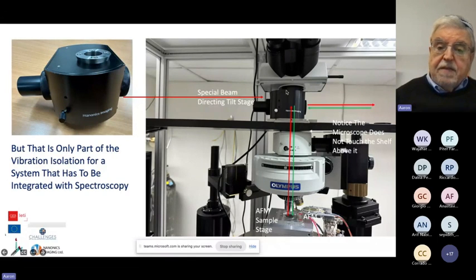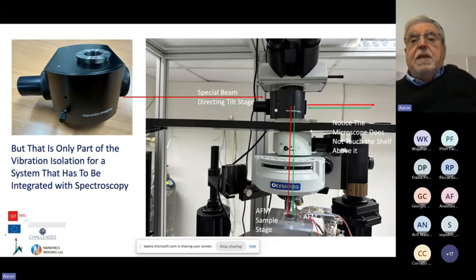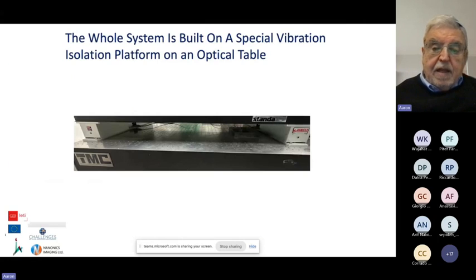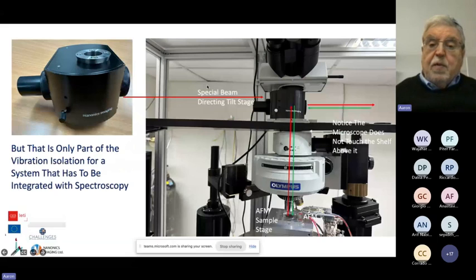Now, this device here is a device that sends the light down from an external source that's coming from the right. That's the green arrow that you see, okay? But what's very important about this is the methodology that we've incorporated to isolate the noises that are connected with the spectrometer. Because if you go back here, all of this is sitting on an optical table. The spectrometer, the lasers, the CCD are also sitting on the optical table, but they're not isolated like the AFM is. The AFM is built on top of this system. So we do something interesting in this design. We have this shelf on which the oculars are. And we make a special device, which is seen here. And this device is not connected.